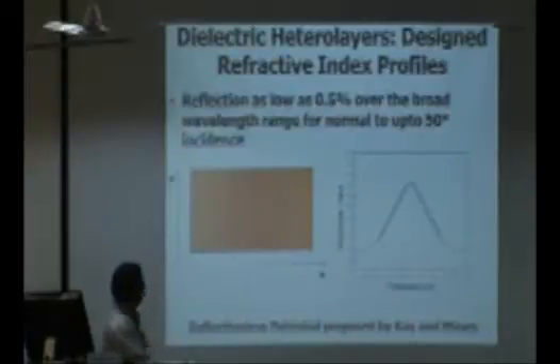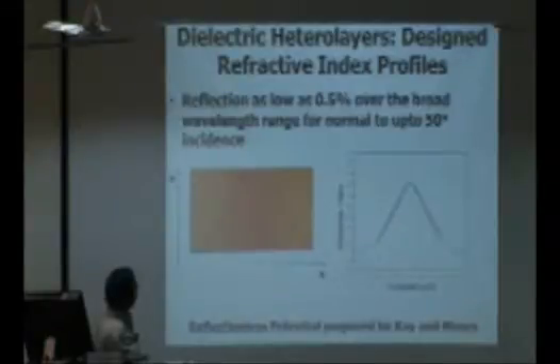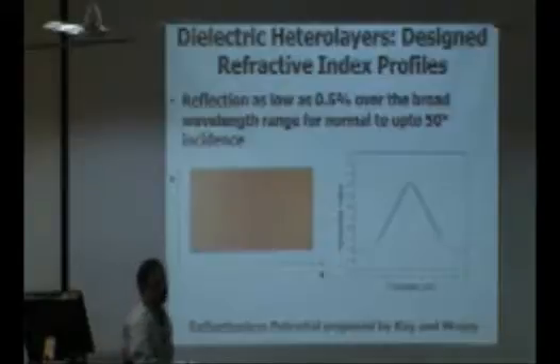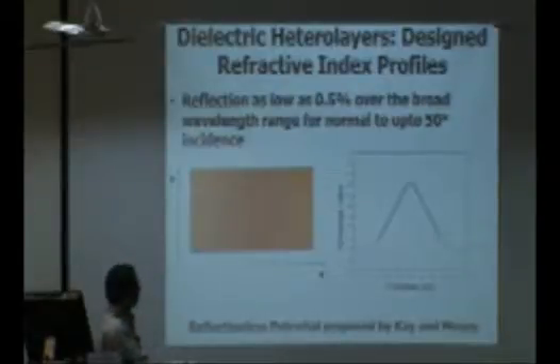So the other work which we do is related to dielectric heterolayers. These are designed refractive index profiles. What we are interested in is broadband omnidirectional reflectionless potentials. What we show is that as a function of thickness, if we can modulate the refractive index, we can suppress the reflections over a broad wavelength range.